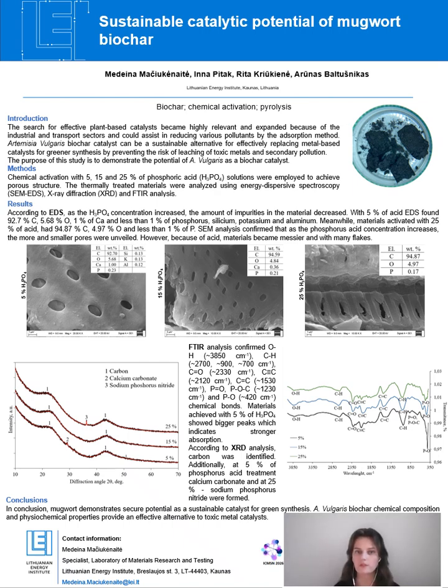A tendency was observed indicating that increasing the phosphoric acid concentration during the activation process resulted in a lower occurrence and diversity of detectable elements in the materials. This phenomenon may be associated with the enhanced removal of inorganic impurities and volatile compounds during chemical activation and also during thermal treatment. Higher phosphoric acid concentrations likely promoted more intensive decomposition of the original biomass structure and facilitated the elimination of mineral components, leading to a purer carbon-rich material and, of course, with reduced elemental complexity.